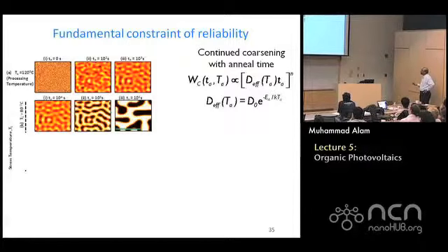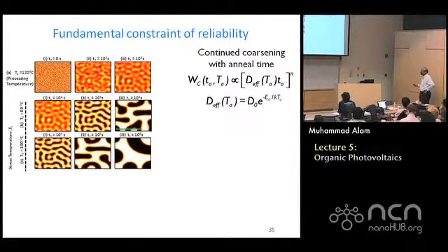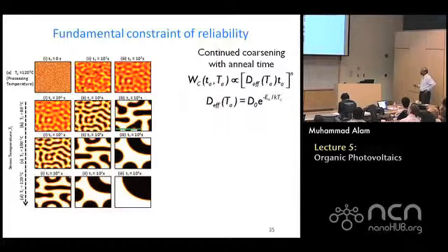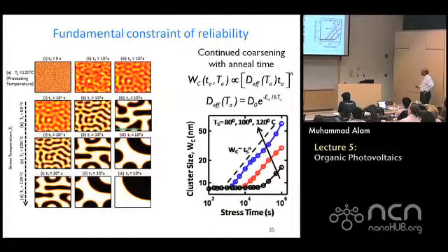So depending on the temperature, if you have 80 degrees, 100 degrees or 120 degrees, these are test temperatures, the phase segregation will continue. The width of these regions is going to get wider, exciton collection is going to get poorer and poorer, and within 1 year, for sure, the cell is not going to work. And this is the cluster size. Remember this T to the power 1/3 I told you about? If you made the temperature high, 120 degrees, this is going to get faster, and on the other hand, if it's lower, it is slower. So in Alaska, maybe things are better for organic solar cells, but Arizona may not be so good.